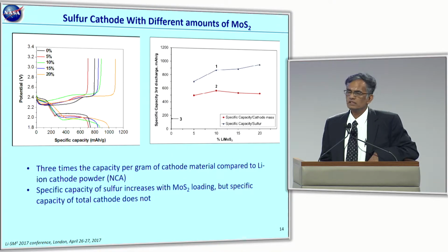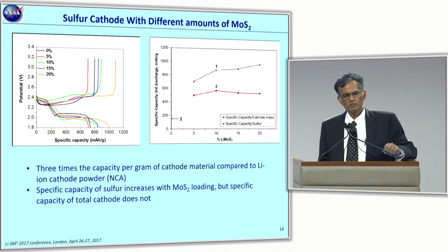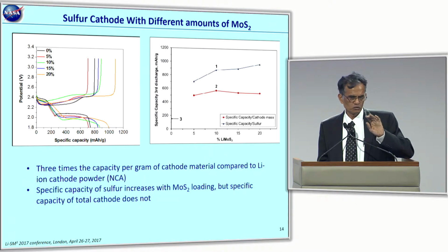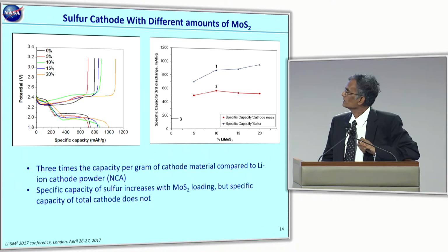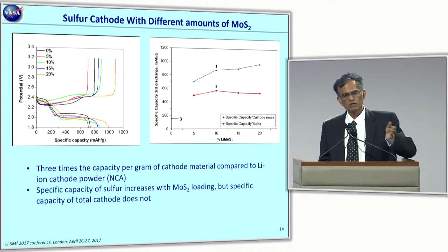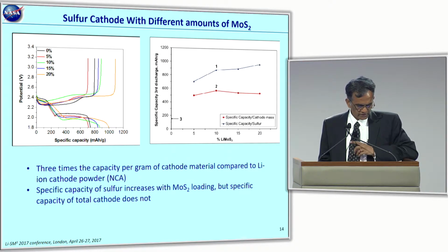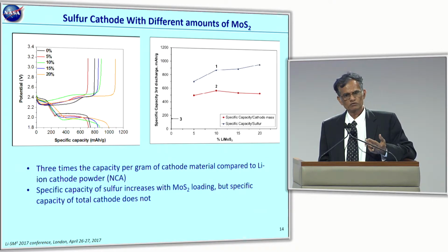Here, we looked at trying to optimize how much MoS2 content we need to optimize the capacity. In all these cases, as we vary the MoS2 content, we kept the carbon content the same so that there's no change in the conductive diluent. We used 20% of the carbon. But then the ratio of sulfur and MoS2 has been changed to get anywhere from 5% to 20% of moly in these cases. As you can see here on the right, the utilization of sulfur actually improves by virtue of having moly as part of the cathode blend.